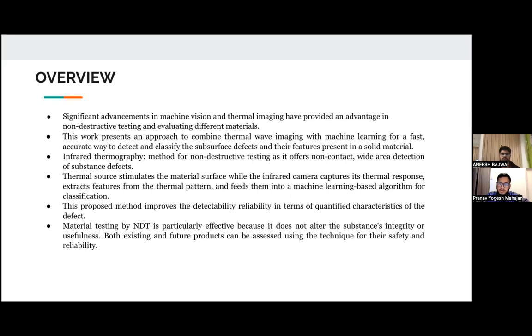Pulse thermography, being fast and simple, remains one of the popular non-destructive evaluation techniques, though it has some limitations. In FMTWI, heating waveform relations are adjusted over a bandwidth B such that a fully modulated chirp, a frequency modulated signal of duration T with much reduced peak power, is produced. It can be processed by matched filtering, that is pulse compression, to improve sensitivity.